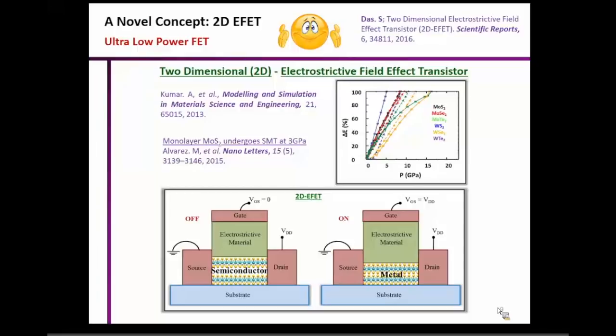Now think about an ideal switch. An ideal switch should be an insulator in the off state, and it should be a metal in the on state. Right? That's an ideal switch, because then you have almost zero power dissipation in the off state, which is an ideal insulator, and you have a lot of on current in the on state. And this is exactly what you can achieve by this kind of device geometry, because now your device in the off state is a semiconductor with large band gap, and in the on state it's a metal, which allows you to flow a lot of current.